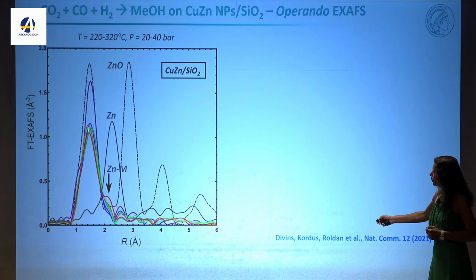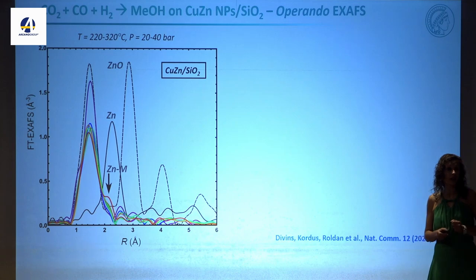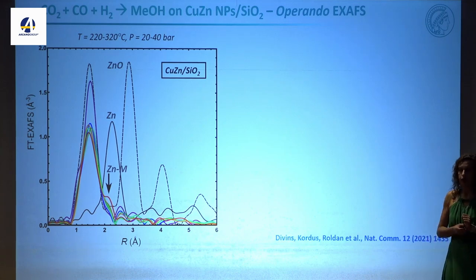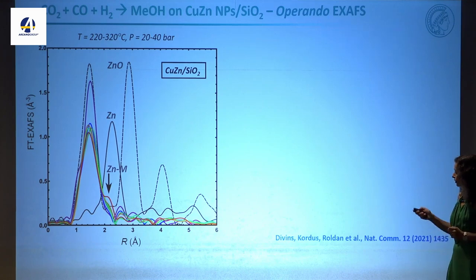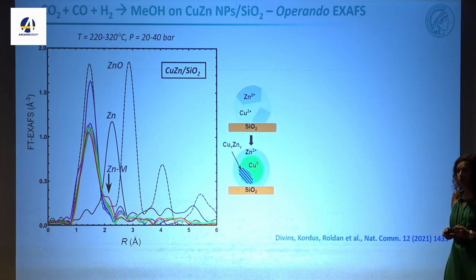Now, this peak here corresponds to zinc-oxygen bonds, and this corresponds to zinc-metal bonds. And under reaction conditions, these shoulders start showing up here. So yes, you are making brass. And yesterday there was a debate whether this is the active catalyst or not. And brass also makes methanol, but not as good as when you have copper in contact with zinc oxide.